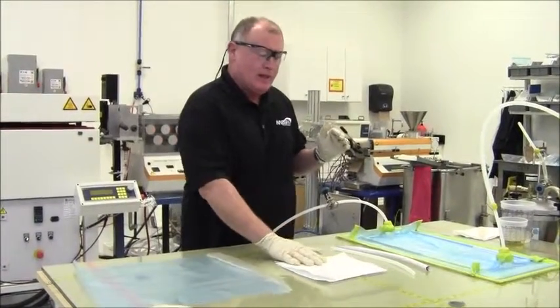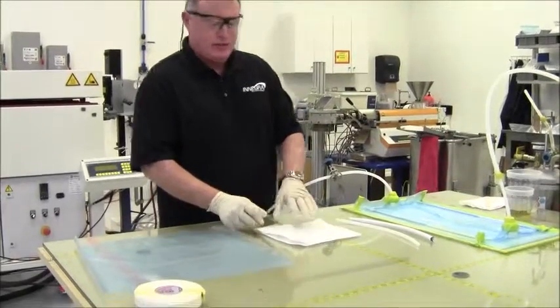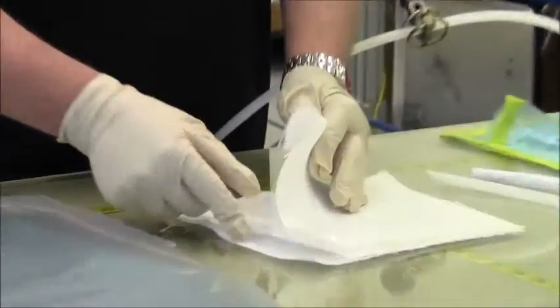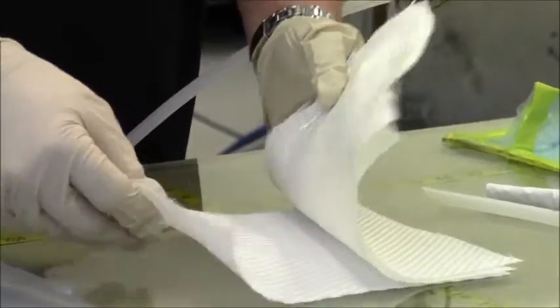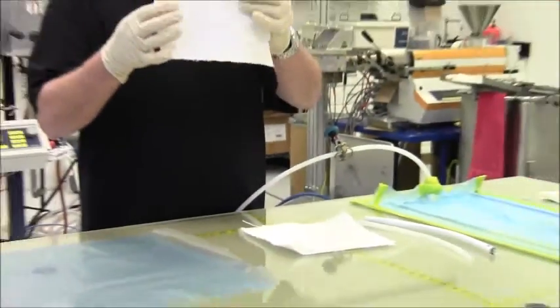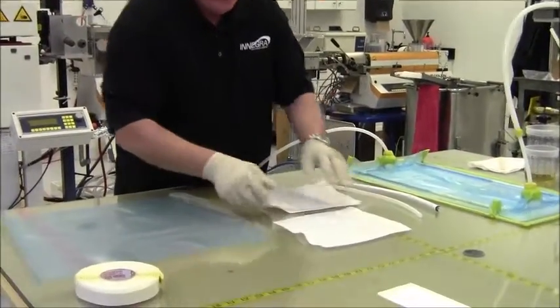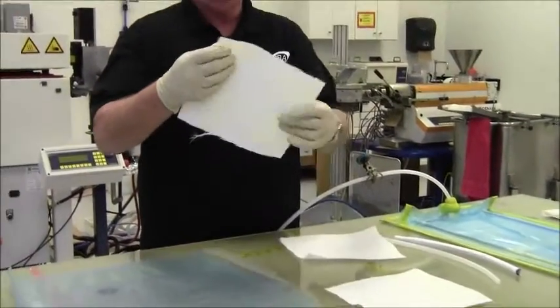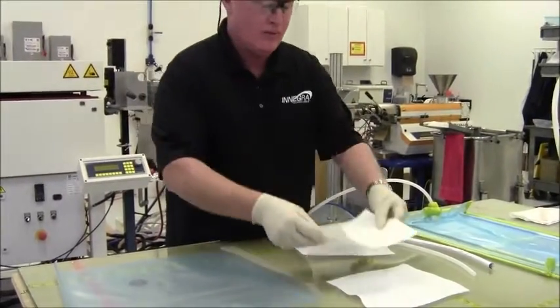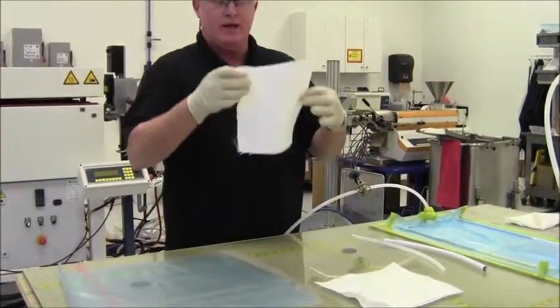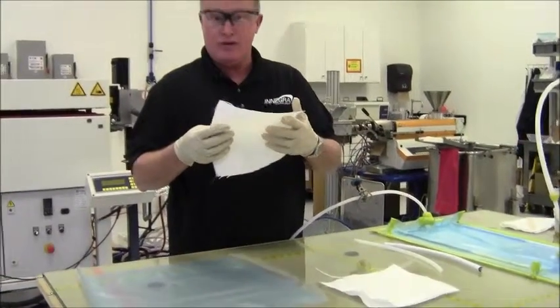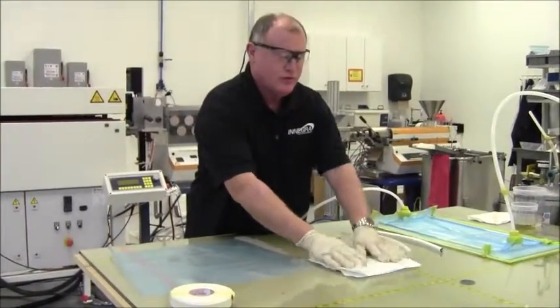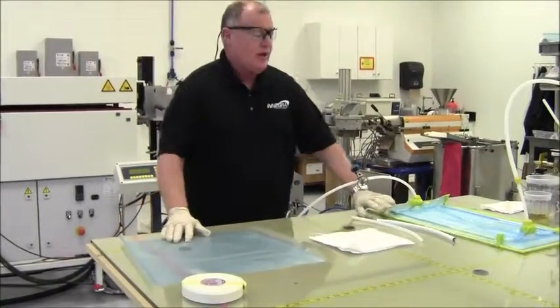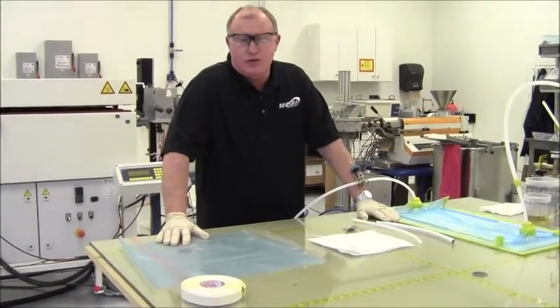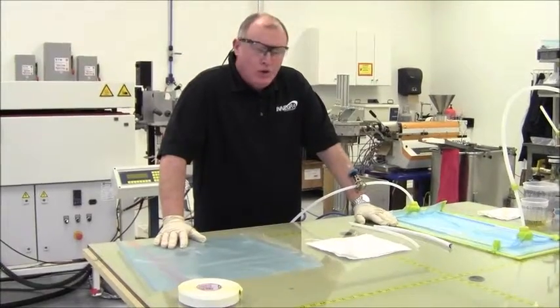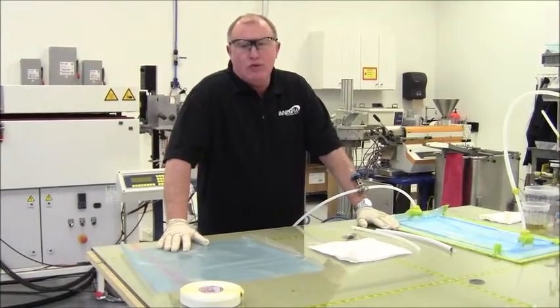Secondly, I did my layup, and in this case, for this test specimen, we used three plies of fabric. One ply of 100% 2x2 twill Innegra. A second ply of a plain weave glass Innegra blend. And a third ply, again, of a 2x2 twill Innegra fabric. The reason for this particular layup is to show you how simple it really is to infuse with Innegra. There's no real complexities that you don't normally run into.